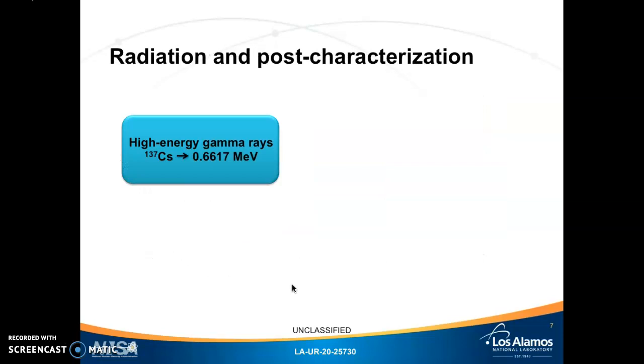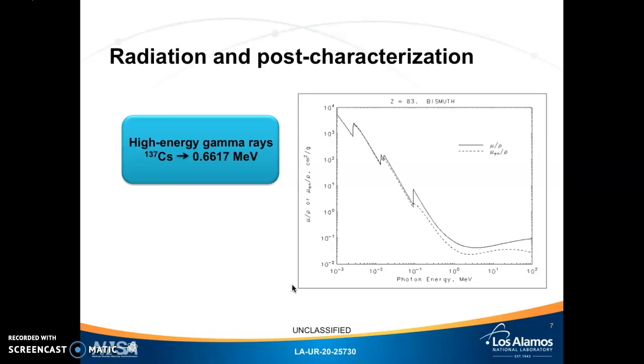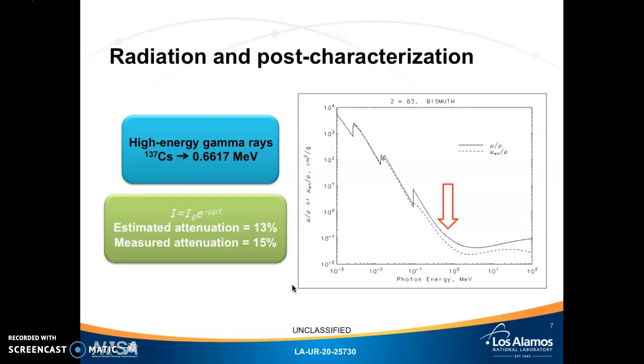Testing the radiation shielding capabilities of the composites was performed using a cesium-137 source emitting high energy gamma rays at 0.66 mega electron volts. Reviewing the radiation attenuation chart of bismuth shows our attenuation coefficient is here, and inputting this as mu along with the incident radiation I, density ρ, and thickness T of our samples allows us to estimate an attenuation of 13% when we measure an attenuation of 15%, which is in pretty good agreement.